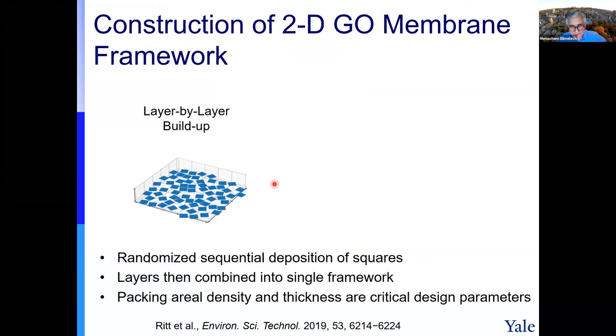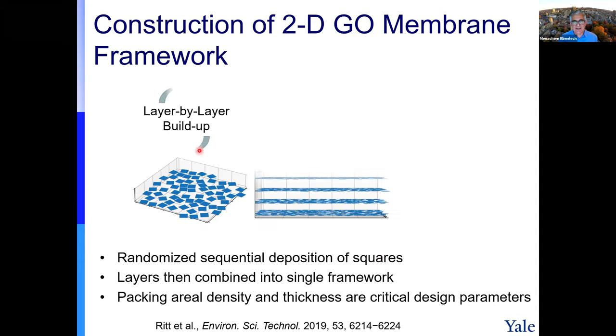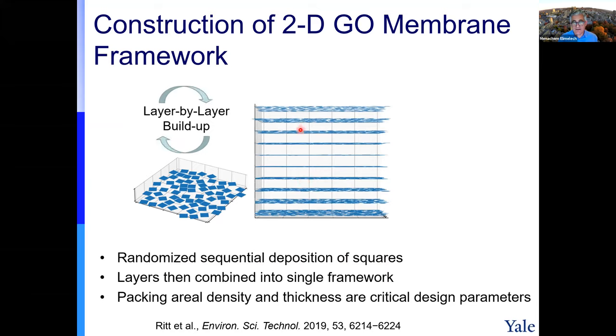So we said, okay, let's study it by a Monte Carlo simulation. We try to simulate the way you make these membranes. And the way you make these membranes, I told you, you take some graphene nanosheets, as you see here. You disperse them in water, and then you vacuum filter them. And when you vacuum filter them, you will form these layers. We try to simulate this process by what we call randomized sequential deposition of these squares. You create these layers one after the other, and you create a membrane.